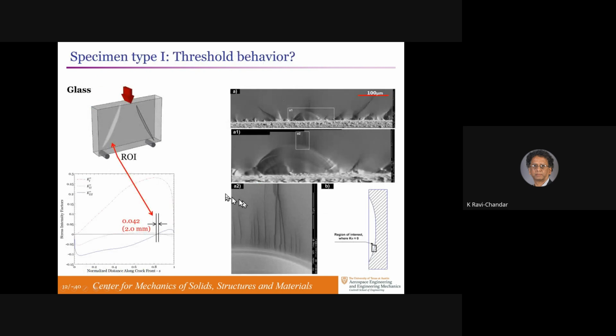So we designed a specimen in which this was a glass specimen, rectangular in shape, under 3-point bending, but with a crack that's slanted at a particular angle, but the crack doesn't penetrate all the way through. It's a 3-dimensionally shaped crack. You can see it penetrates the surface on the back side there. It's a circular arc and penetrates again over here. In this side, it's on the opposite face. And this is to get different symmetries of K3 to K1 on the two sides. And we were able to calculate the stress intensity factor very precisely for the 3-dimensional problem using a boundary integral technique.